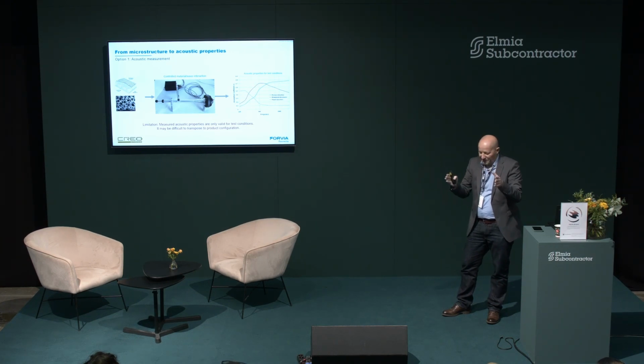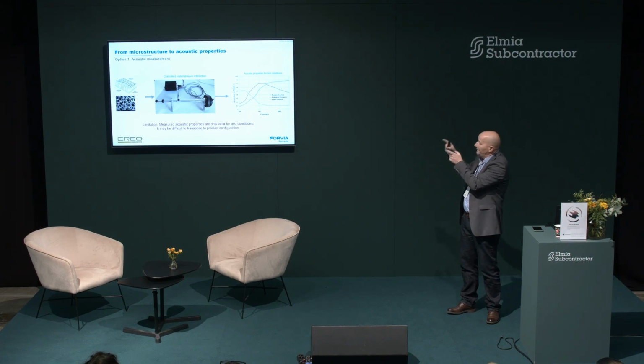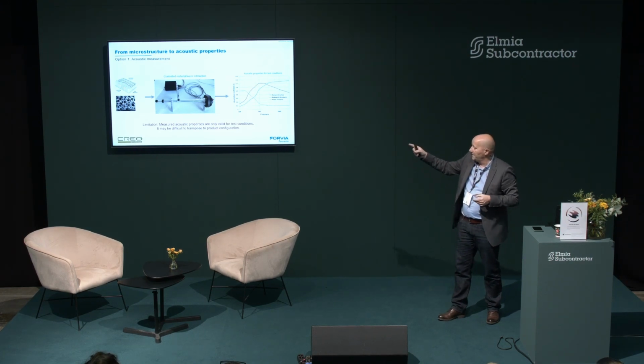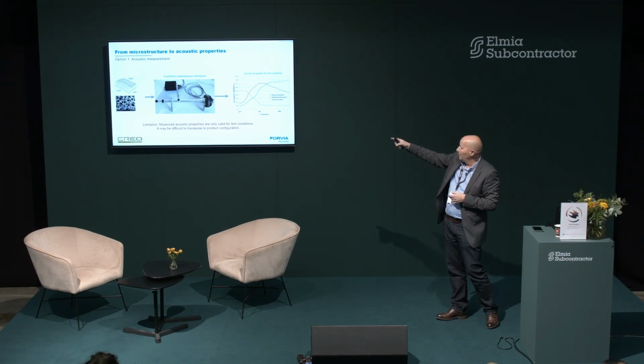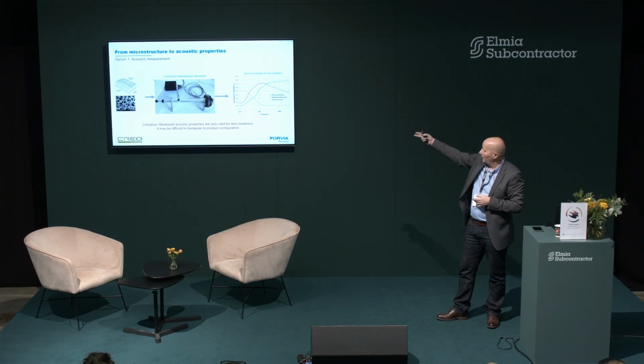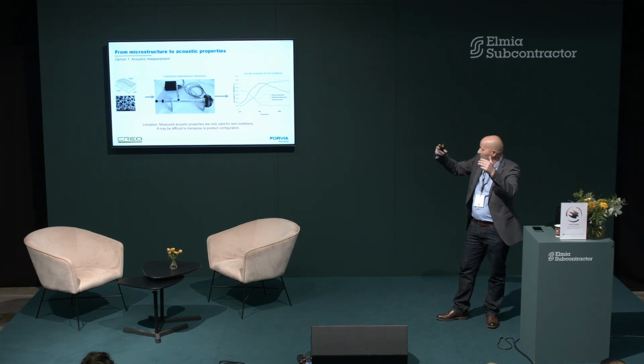And this simple case gives us very clear and quantitative information about the acoustic properties of the material. Typically, from this configuration, you can get an absorption curve, which is often a function of frequency, where you know when you have an absorption of 1 it gives you a total absorption, and you see the behavior.